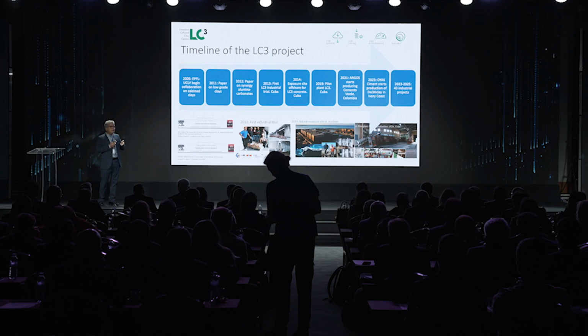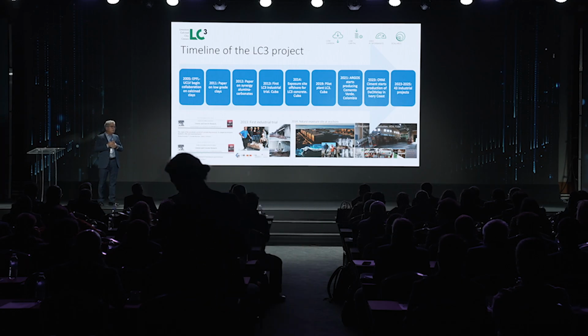So after 5 years of direct work, there were two main papers published. One was the paper on low-grade clays in 2011, and soon later, in 2012, the paper on the synergy between alumina and carbonates. That was the backbone of the LC3 concept. And very, very quickly, we were able to scale it up at the industrial level.